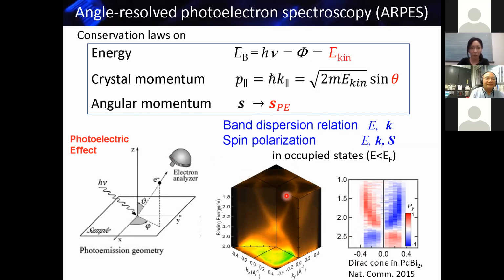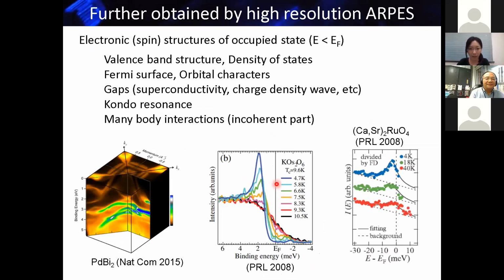And what we can further obtain by this photoelectron spectroscopy is that if we look into the detail, besides these valence band structures and Fermi surface, we can also look at the orbital characters of these wave functions composing the Fermi surfaces and bands. And also, if we have a good enough energy resolution, we can look into the gaps, like superconducting gaps. This is the superconducting gap spectrum in this osmium pyrochlore system.